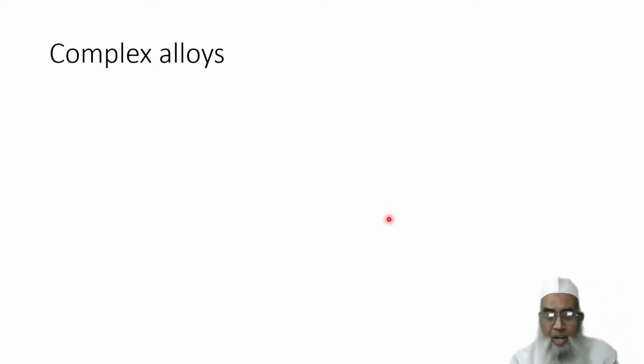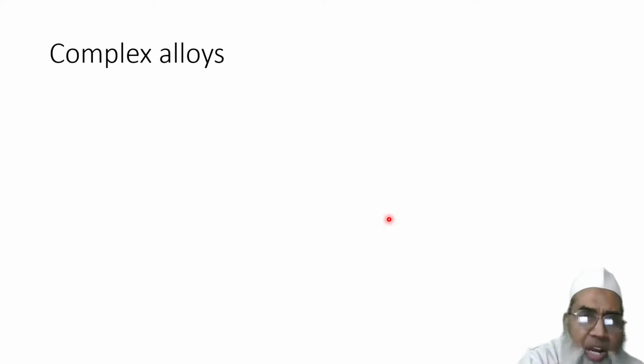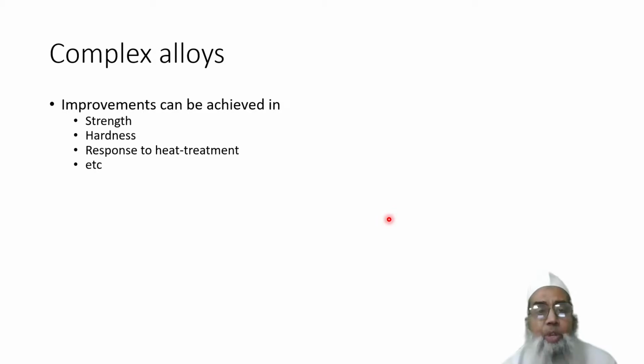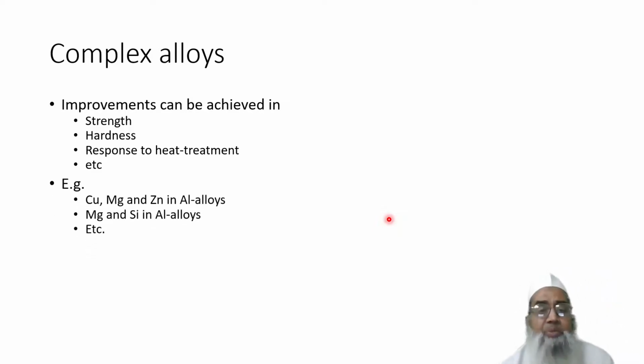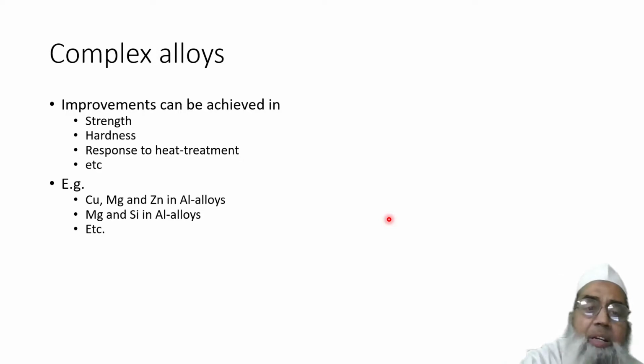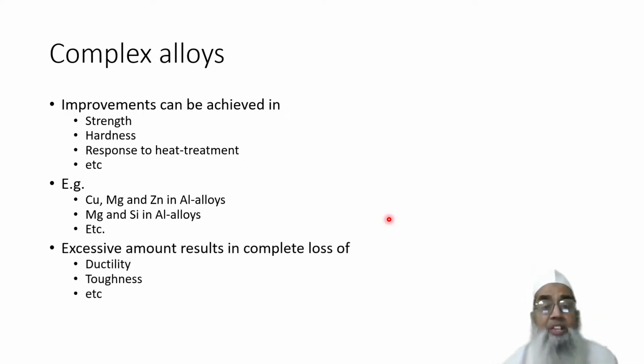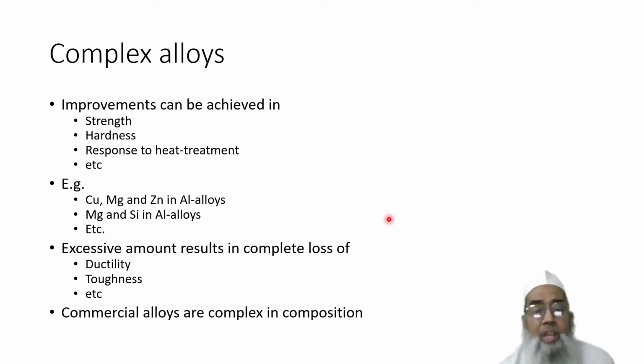Then we can have, as we have talked about, silicon, magnesium. Similarly, we can enhance the properties of aluminum alloy by having a complex alloying system, which can be achieved to improve strength, hardness, response to heat treatment, etc. As we have seen, copper, magnesium, zinc in aluminum alloys, and also magnesium and silicon. Similarly, we can have different complex systems, and we can have different properties tailored according to our requirement. However, an excess amount of all these in the complex system loses ductility and toughness. Therefore, we have to make a compromise. The commercial alloys have a complex composition.